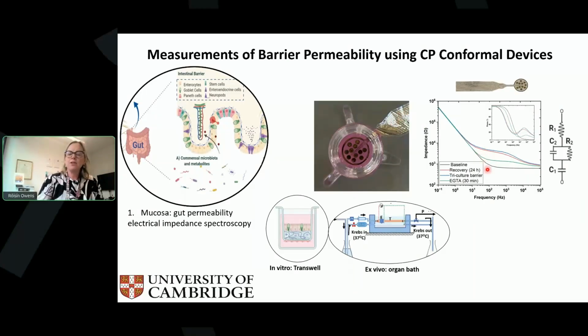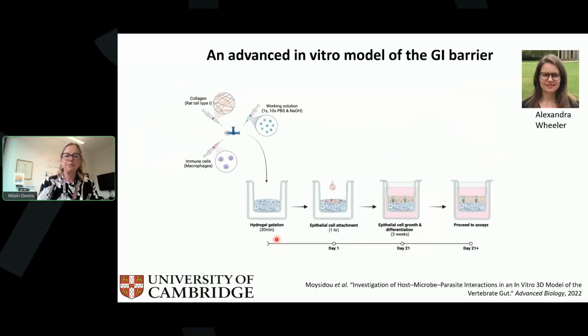If I show you the data here on the right, what we've got is the baseline, which is the bare electrode. When we take our electrode and place it on top of tissue, we expect to see a shift upwards in this mid-frequency range. I can go through the data in a second. We extract the resistance, which is this resistance here. We can do that in vitro on a transwell, and we've actually shown we can do that on pieces of tissue ex vivo in an organ bath.